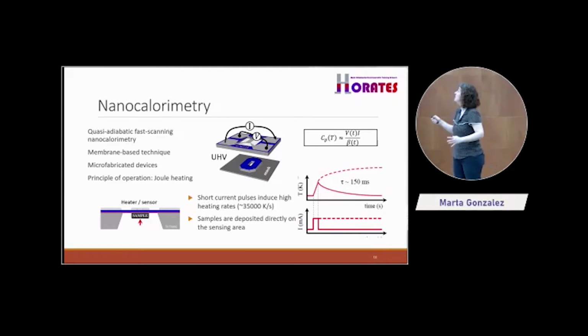all the heat, I mean, since this is a membrane and it's very thin, something like 150 nanometers, all the heat that the sample takes or releases during the transition will go into the platinum. We don't need extra heat to heat all the system. Our system is not contributing what we call thermal mass because it's very thin. Its mass is very small, so heating it up is nothing. We don't need almost any heat to have the system equilibrated. Okay, I can go into the details later if this is not clear.